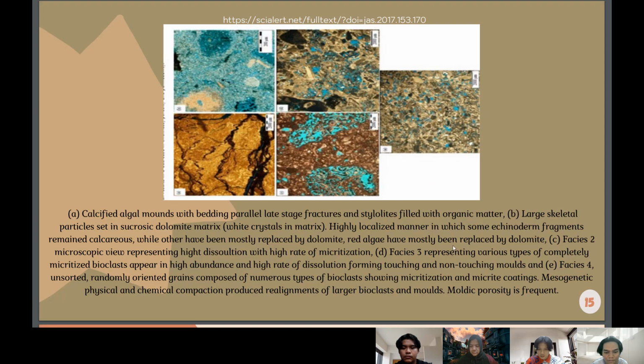Okay, next. Firstly, for diagram A, stylolites and solution seams are the products of chemical compaction. Sucrosic dolomite, for which a local source of dolomitization was responsible, formed from high coralline red algae content. For your information, these dolomites represent very good reservoir quality. To conclude from this diagram, facies 2, 3, and 4 are the potential reservoir facies, except for the occasional development of non-touching moulds and micritization. Micritization is a diagenetic process that affects the quality of the reservoir, as it destroys the internal structure of the grains and reduces the porosity in almost all of the phases, except for phase 2, where the rate of micritization is higher compared to the other phases.